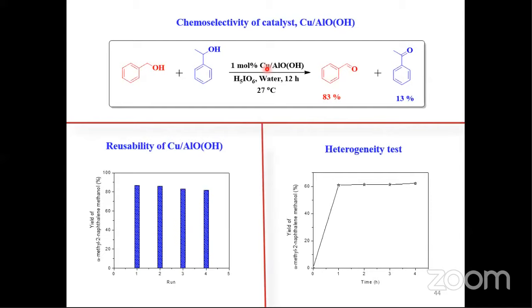In a single substrate, if you have two different alcohol groups, when you add this catalyst, this will oxidize only the primary alcohol, whereas oxidation of the secondary alcohol is very meager, right? So this again demonstrates the selectivity of the nanocatalyst. And again, the catalyst can be recovered and reused. This is the heterogeneity test.